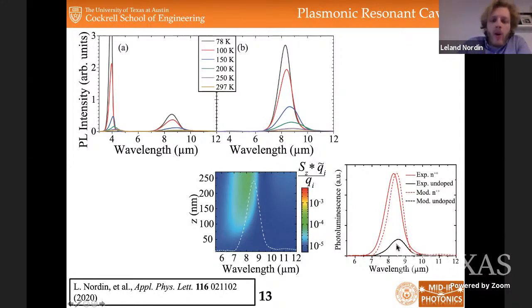And we're incorporating all these dopants, does that compromise the optical quality and ruin our emission, or potentially ruin our detection or ability to collect photocurrent? So the first experiment we did was we grew 2 samples, one type 2 superlattice on an undoped virtual substrate, and then another one on a highly doped plasmonic material substrate. And that's what's shown here. And then we performed photoluminescence measurements on both of them.